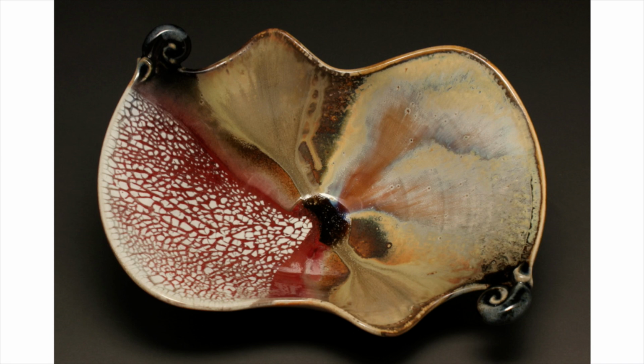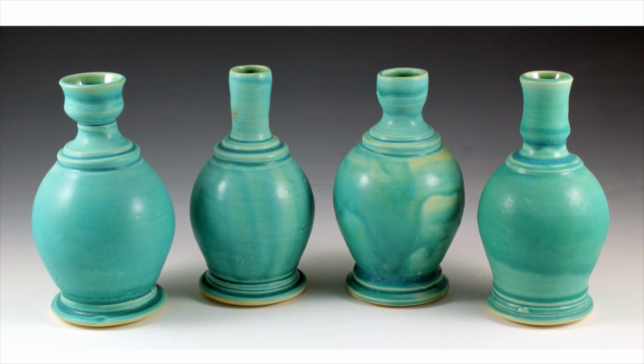How the glaze is applied, as in this image—dipped, poured, brushed, or sprayed—is very important. Each of these methods applies the glaze with slightly different thickness, which can dramatically affect the outcome. Even how thick or thin the glaze was originally mixed, what temperature the piece was fired to, how thick or thin the clay body wall was, and even how long you hold the piece in the bucket of glaze all affect absorption and therefore the outcome.